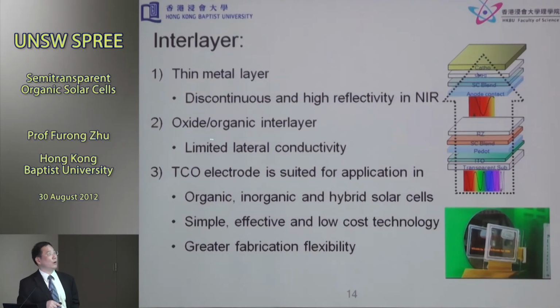The other one is the so-called oxide and organic interlayer. Some of the oxide, when you evaporate it, has a relatively good conductivity and is also transparent, but there's still a limit in terms of lateral conductivity because essentially the current will be passing through. And in our group, we use a material called transparent conducting oxide, essentially ITO or indium doped zinc oxide, for example. This is very suitable for application in that kind of device.